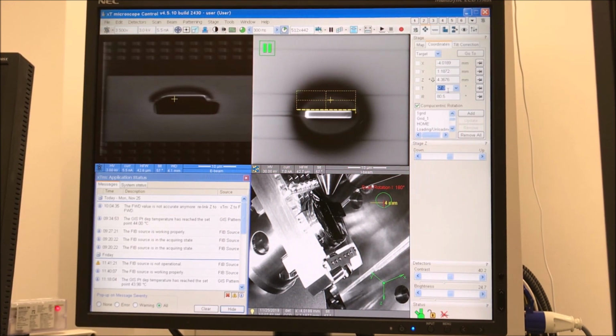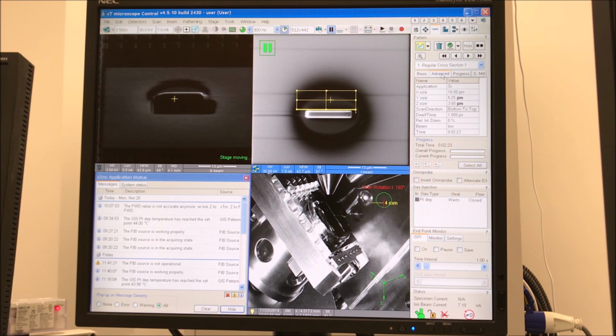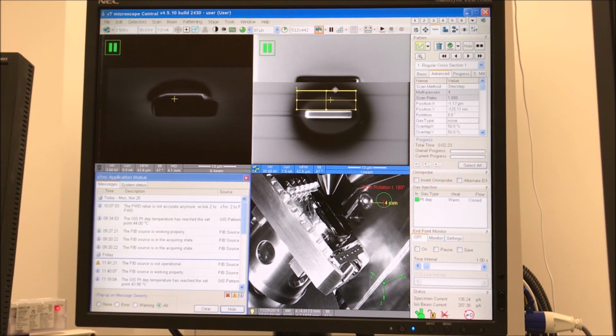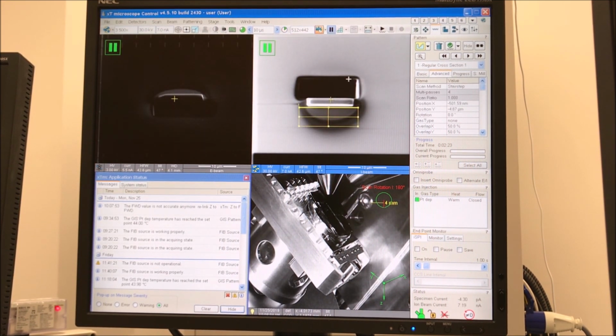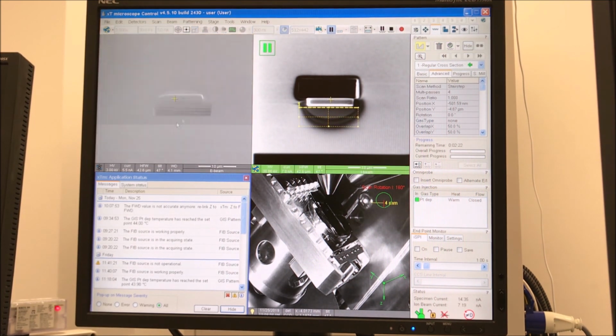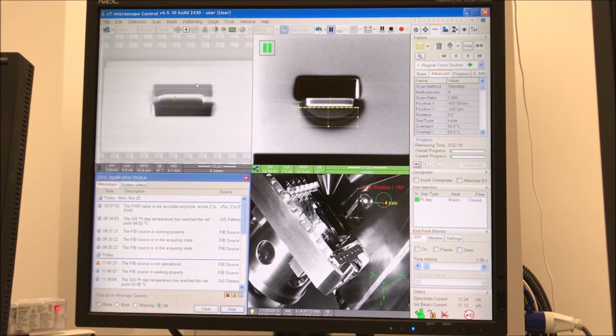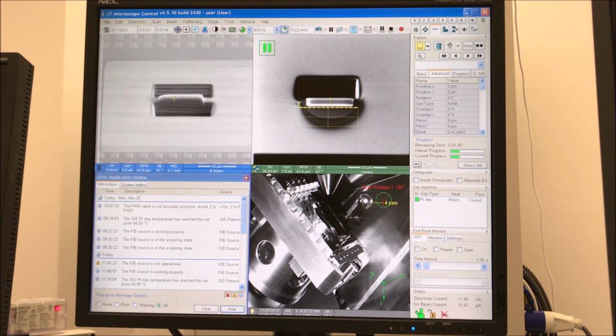Obviously, if you were doing this with a softer material or a harder material, then you would cut deeper or shallower respectively. So now I tilted 5 degrees the other way to 47 degrees, and I rotated the pattern 180 degrees, and I executed the same pattern but from the bottom.